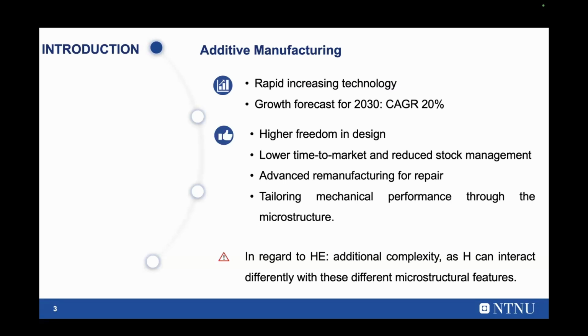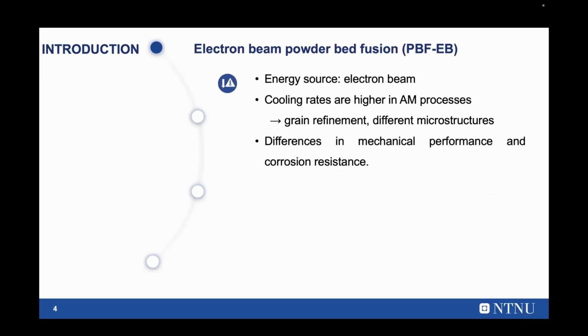Nevertheless, in regard to hydrogen embrittlement, it adds another complexity factor, since hydrogen can interact differently with these different microstructural features that are highly dependent on the manufacturing route, on the additive manufacturing technique, since it gives these complex thermal cycles that lead to different microstructural features. And therefore, even though this alloy has been previously studied for conventional alloys, the knowledge cannot be directly applied to additive manufactured ones.